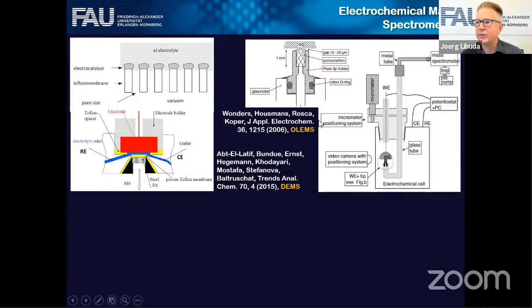So if you want to do that, you can do this so-called OLEMS experiment that has been introduced by Marc Koper's group. Here, what you do is you use a single crystal, and then you come with a capillary that has this membrane built in from the bottom side and bring it in close contact to the single crystal. So this really works with the single crystal.